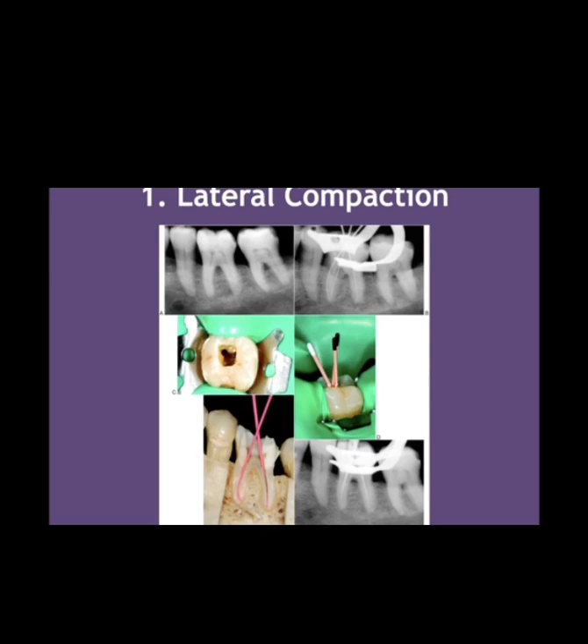And then you go again with the same spreader, and you go step by step until you fill the canal. You go with the spreader, then you get it out and you put another cone. If you suddenly find a jump in the gutta percha, this means that this spreader can no longer be used. Take this spreader 35 away and get the spreader 30 and go deeper. And when you use spreader 30, you are going to use accessory gutta percha 25, and you follow step by step. If you find another jump, you take the spreader out, decrease the spreader size, until the canal is filled completely up to the orifice of the canal.